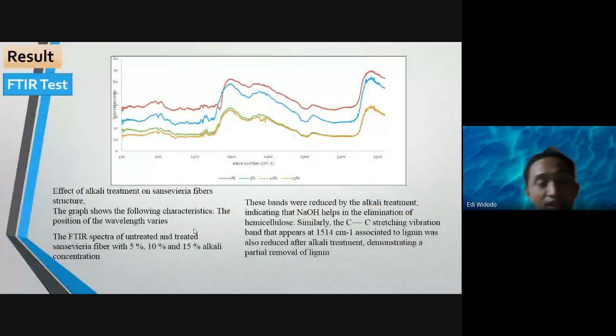This is the result we measured from the FTIR test, Fourier transform infrared test. The effect of alkaline treatment on Sansevieria fiber structure. The graph shows the following characteristics. The position of the wavelength varies. The FTIR spectra of untreated and treated Sansevieria fiber with 5%, 10%, and 15% alkali concentration.